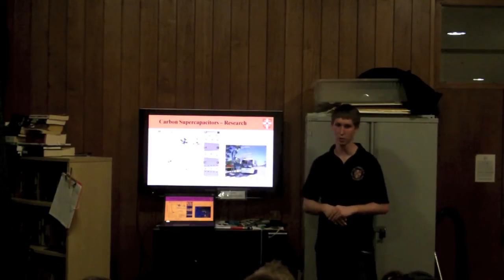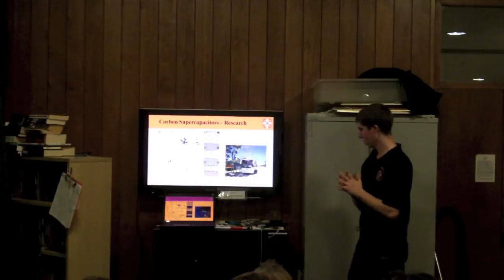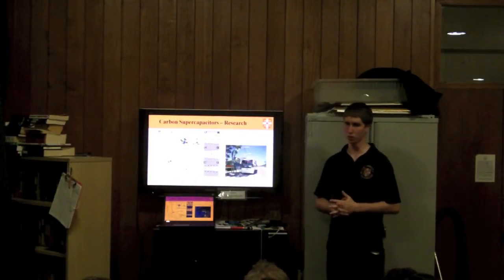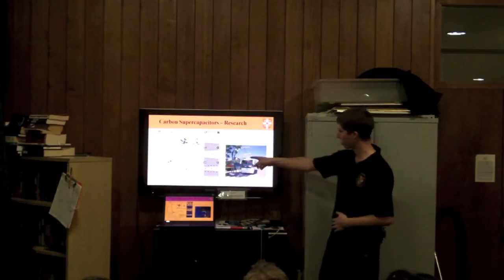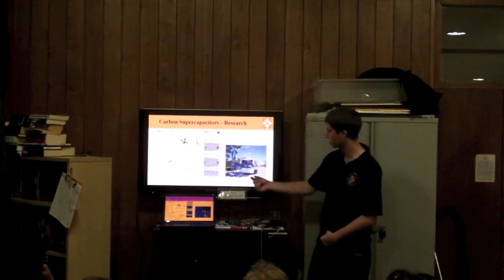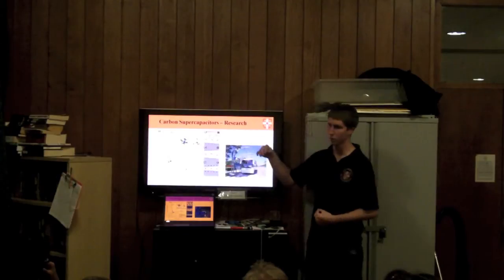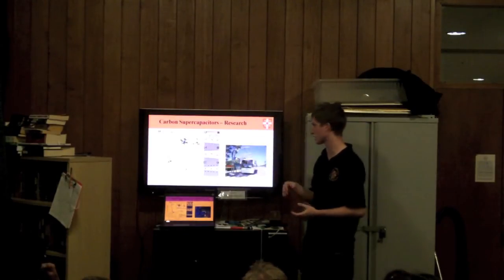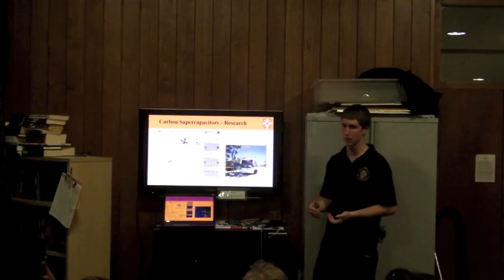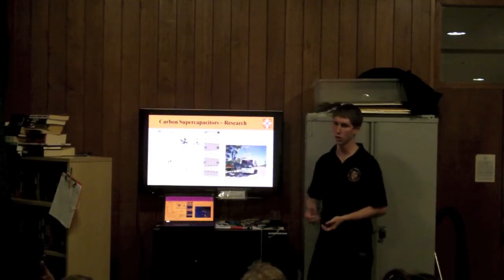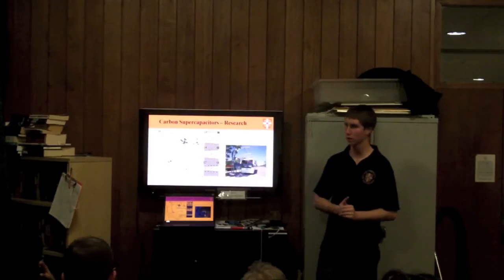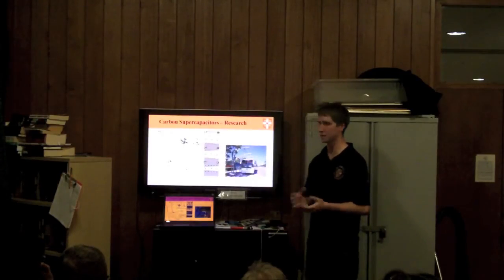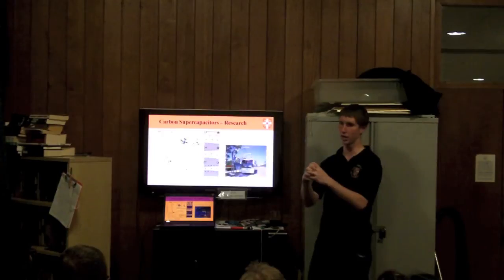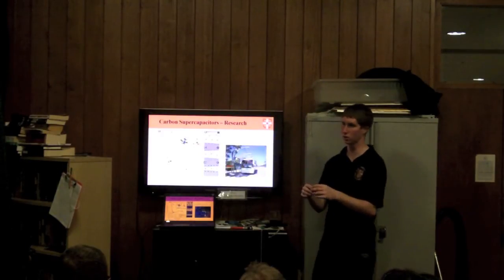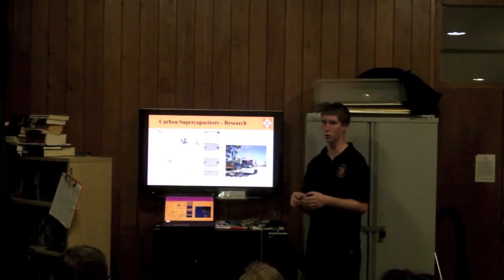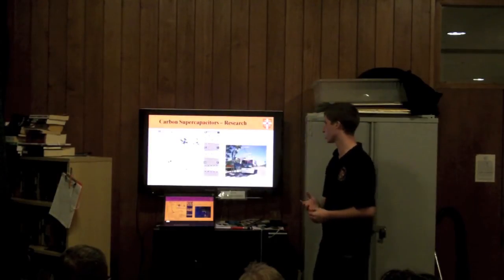But on the research side of things, this was a really big breakthrough that came about 6 or 7 years ago and really brought supercapacitors into real use. What people thought, these white dots, was that as your pore size gets smaller, at 2, 3, 4, 5 nanometers, those are good pore sizes, because as it gets smaller, probably it's going to keep getting less and less, and so maybe we should use something like 3 nanometers as a pore size. That's about what an ion with its solvent around it, whether it's water or whatever, is, about 3, 4, 5 nanometers. So they thought that's good.